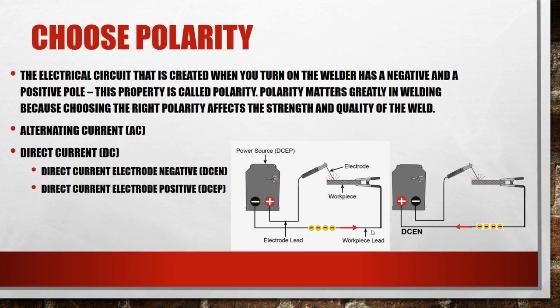Now you can see from the two diagrams between DCEP, which is electrode positive, and DCEN, that the only big difference is which way the electrons travel. Depending on the way those electrons travel, the heat concentrates in a different area. And so, weirdly enough, the heat concentrates where the negative is. So in DCEP, we see the workpiece being where the negative is, I think you can see that in the diagram, which means that that's going to provide greater penetration. In DCEN, we see the negative is where the electrode is, and so we see more heat being produced there.